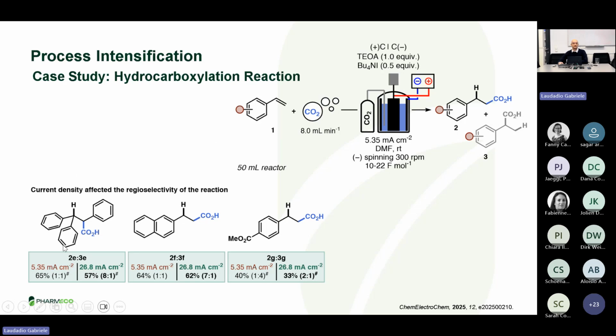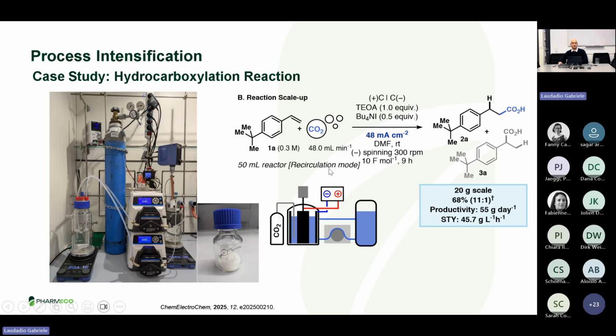Another important thing that we observed here was that by adjusting the current density, we could also obtain different selectivity in terms of hydrocarboxylation, anti-Markovnikov or Markovnikov. And this is due to the unique combination between high mass transfer and the high current density. We obviously also scaled this reaction up in recirculation mode, where this is the reservoir, and this is our reactor that is submerged into a liquid to keep the temperature stable. And we could obtain a productivity of 50 grams per day, and we ran the reaction at around 20 gram scale.